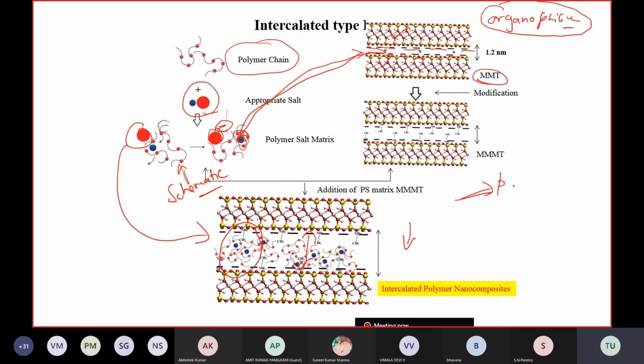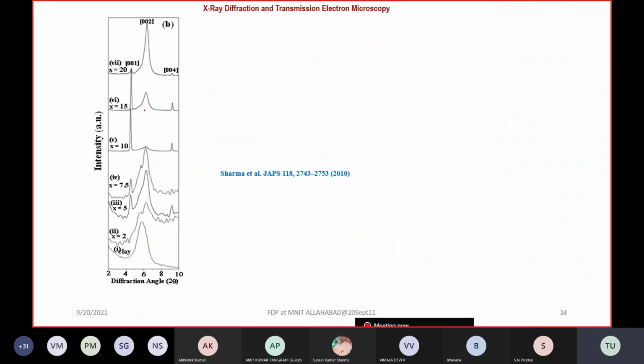So for that reason, I'm just moving a little bit into my core research, what your students have already done here. It is small research, so I'm just moving through this analysis, but not in depth. I will not go deep, but I'll make you understand what different characterizations need to be done in order to prove whether intercalation has happened or not. When you prepare the sample, either solid polymer electrolytes or the electrode or whatever, people look at XRD to see whether it is structurally stable or not. I am showing here only the 2 to 10 degree XRD pattern, performed with a copper K alpha X-ray source.